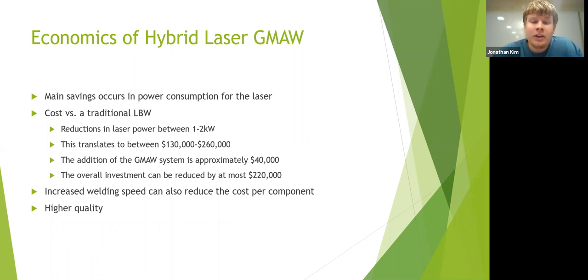The economics of the hybrid laser gas metal arc welding system are actually very good in terms of being compared to a traditional laser beam welding process. The main savings here actually occur from the laser itself. This is because the power consumption is much less whenever it is in the hybrid state. The reduction in power can be between 1 to 2 kilowatts for the laser itself, and this translates to between $130,000 and $260,000. So the addition of the gas metal arc welding system is approximately $40,000. So that's an increase into the cost. So a net reduction to the overall cost is about $220,000 at its max.